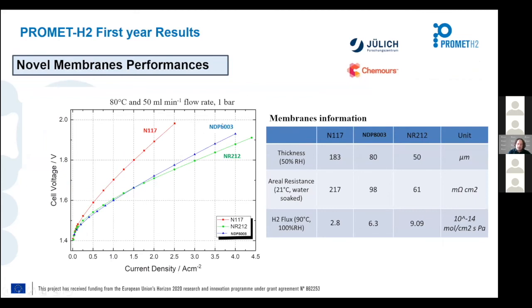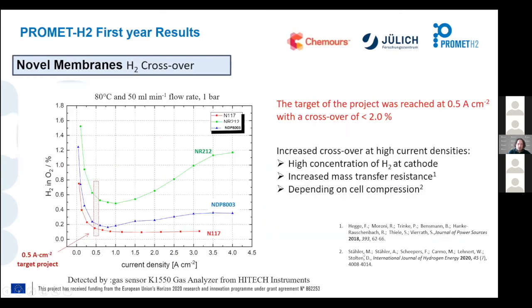And you can see here that the new membrane has a really good performance close to the thinner membranes of Nafion 212. And regarding the hydrogen crossover, the behavior is closer to thicker membranes like the Nafion 117. I think it's a really promising membrane. And also with these results, we achieve the target from PROMET-H2 regarding the membrane.